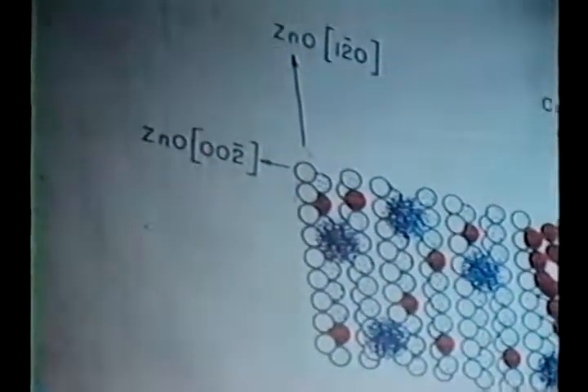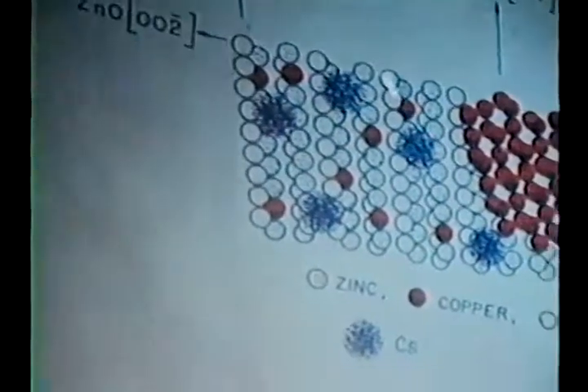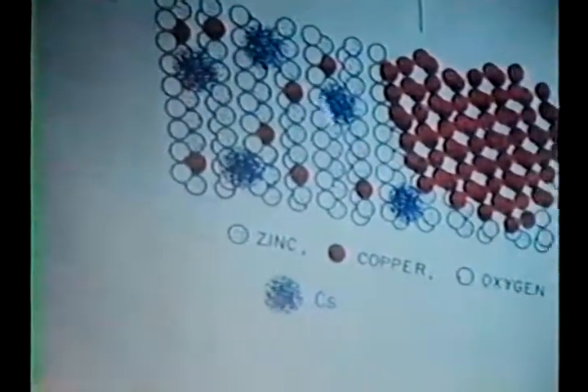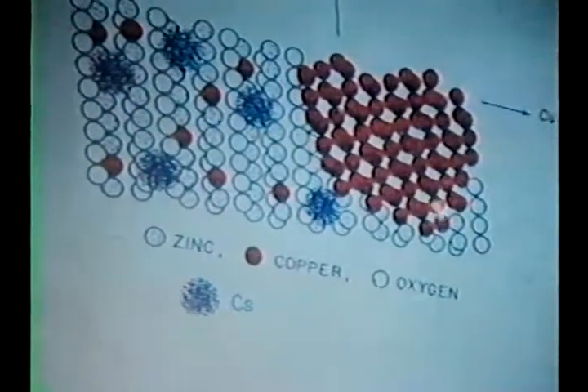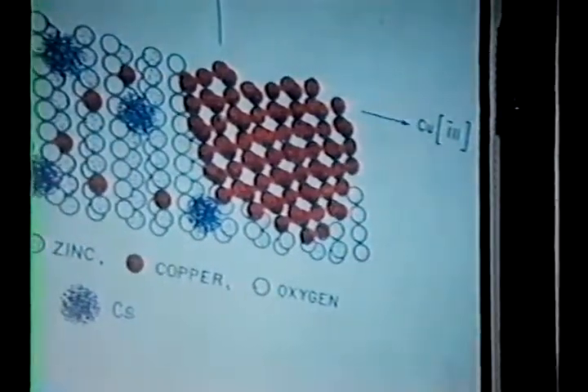Where is the cesium on the copper catalyst? It's dispersed primarily on the zinc oxide phase. It's not on the copper particles. This picture comes from a combined XPS and electron microscopy study, and we were allowed to publish rather quickly in Journal of Catalysis. There are copper centers which are centers for irreversible CO chemisorption, whereas the copper particles here only chemisorb CO reversibly. That is the approach that we followed from Nixon's work on reversible and irreversible hydrogen chemisorption.